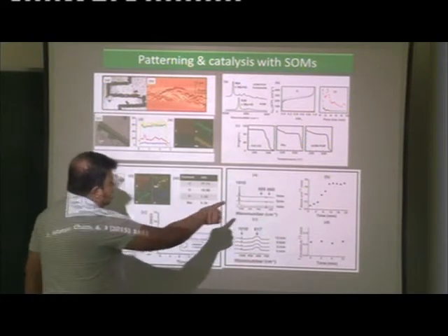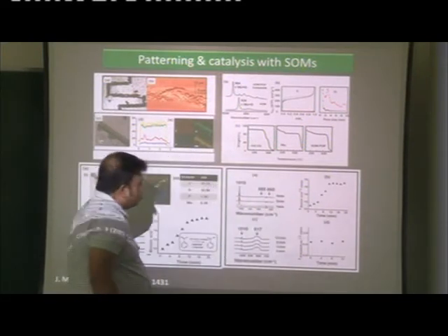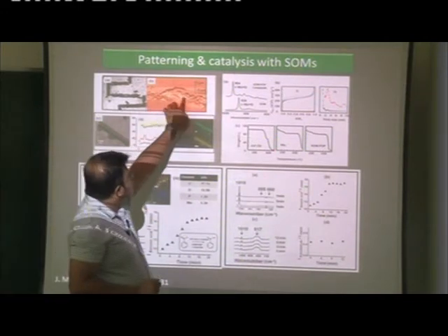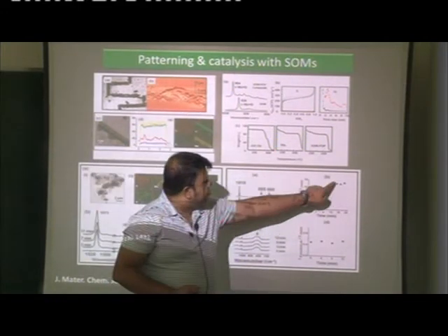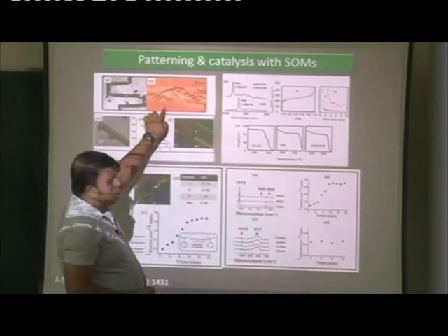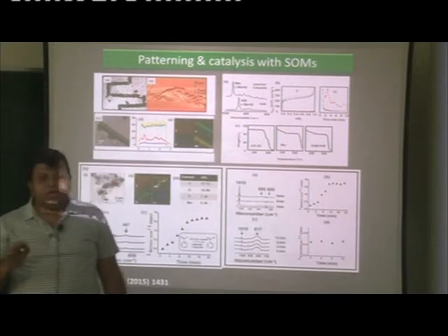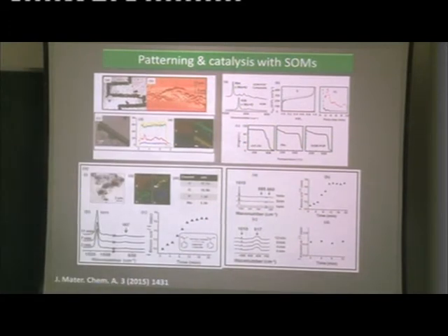And we could see again another heterogeneous kinetics in operation. What was interesting is that if we do the catalysis on the trail, we do see heterogeneous kinetics, but if we do the catalysis away from the trail, that means away from the surface of the active material, we do not have any catalysis. So that means it is very, very site selective. So we now intend to do more site selective combinations of different types of catalysis on the chip.